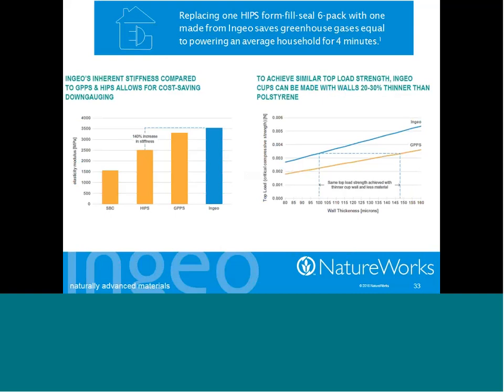Well, what are the other attributes of PLA that would make somebody switch from these high impact or these clarified polystyrene formulations to a PLA? One attribute that we have is our stiffness. If you look at the graph on the left here, the stiffness or the modulus of PLA is about 40% more than a typical high-impact polystyrene that would be used to make these, in this example, yogurt cups.